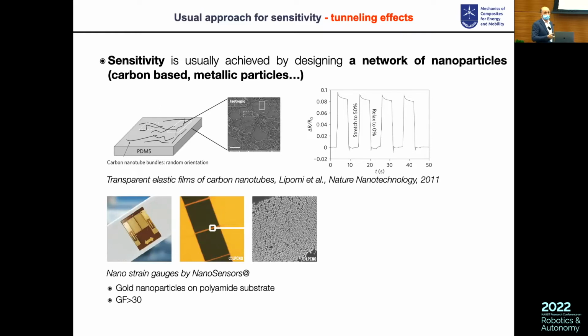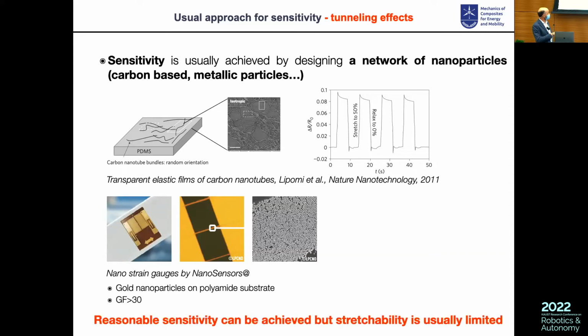Another way to use exactly the same concept is to use clouds of metallic nanoparticles. This is what you call, for example, nanosensors, in which you have metallic nanoparticles touching each other on a polyimide substrate. With this same concept, you get a high gauge factor, around 30. But of course, you are on a polyimide substrate, so as soon as you stretch your substrate a little bit, you separate the particles. So you have a very small stretchability. That means there is no solution. Either you have a small gauge factor and big stretchability, or a high gauge factor and small stretchability, but nothing can sustain a high stretchability with a high gauge factor.